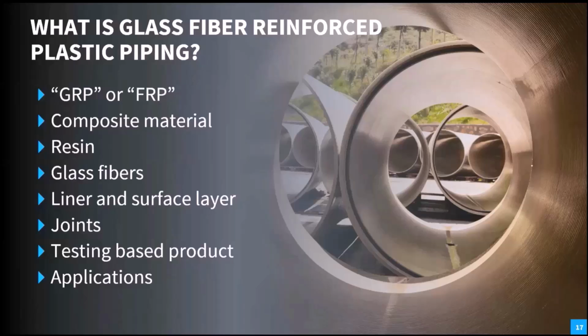Thermosetting means when cured by application of heat and or chemical reaction, it changes into a substantially infusible and insoluble material. The resin brings the environmental and chemical resistance and is the binder for the glass fibers in the structural laminate. The glass fibers, normally E-glass, add strength to the composite. Next to the structural wall of the pipe, there is normally a resin-rich liner for additional chemical resistance applied. In some cases even a thermoplastic liner is required. On the outside, a surface layer with UV inhibitor can be applied. Joints are typically made by means of lamination, by adhesive bonding, by butt and strap, with rubber ring or a flanged connection.